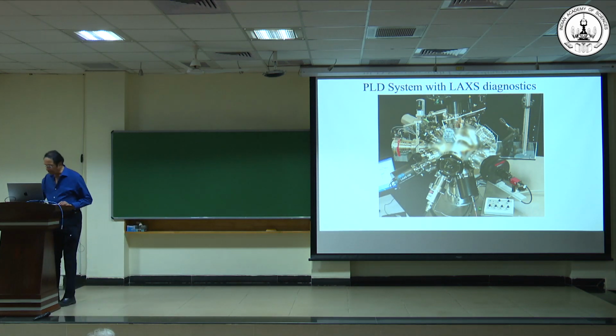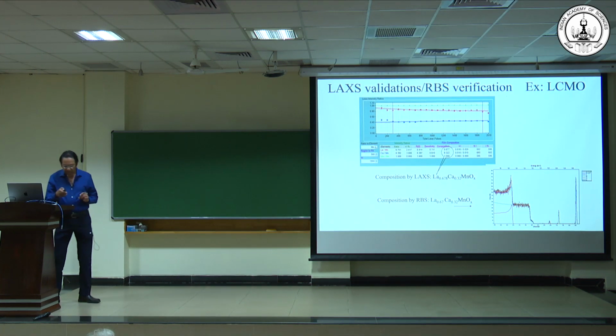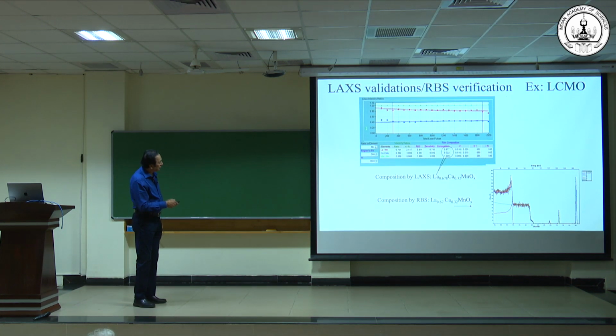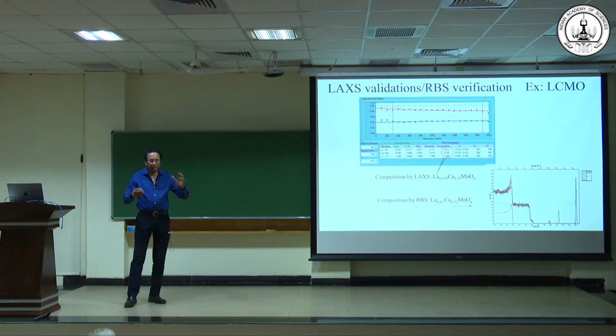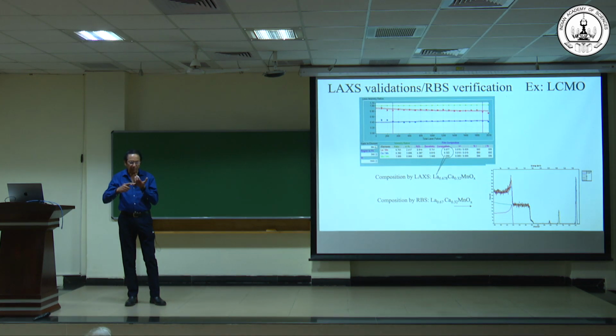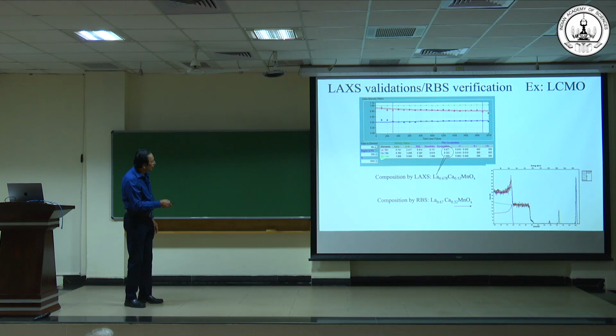So now, I just want to show you the results. And the way it works is, we measure the X-rays produced as a function of time, and we extrapolate the X-rays produced with a characteristic to 0 thickness, basically. At 0 thickness, essentially, all the problems like self-absorption of the fluorescence, and re-emission from different depth areas, all of these problems which cause confusion go away. So you essentially go to the 0 thickness approximation. So this algorithm, that's what it does. As the film is growing, it constantly extrapolates back to 0 thickness and gives you the composition.